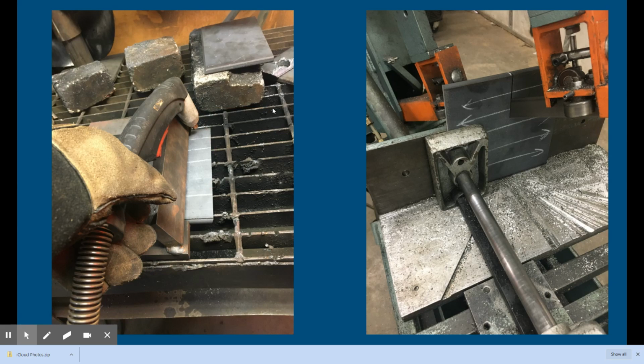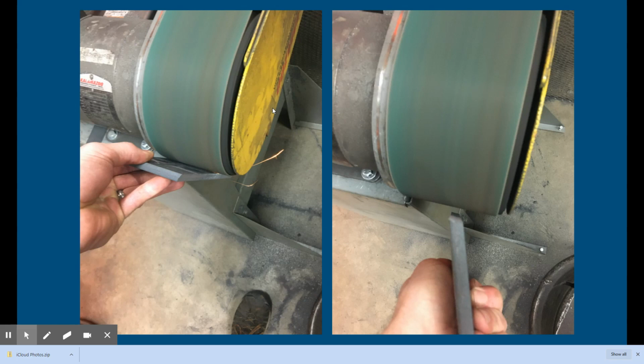They do require a little bit of cleanup, though. Bandsaw cuts them pretty clean. You don't really have to spend a whole lot of time cleaning up the actual bevel itself. But it is possible to do it either way. After you cut your coupons, I do like to clean them up. We have a belt grinder that we'll take, and I'll clean the actual bevel itself, and just kind of start at the top and just slide the piece all the way up, get all the way down to the bottom. And then I'll take mill scale off both the back side and the front side.